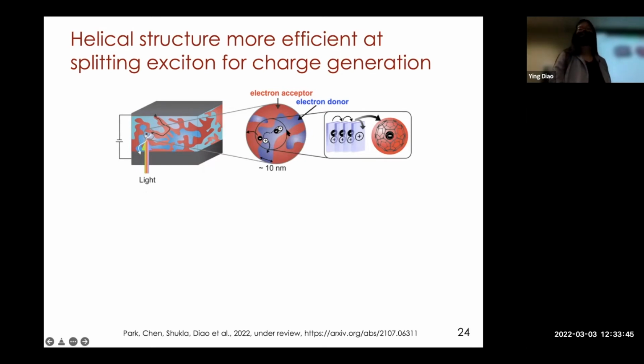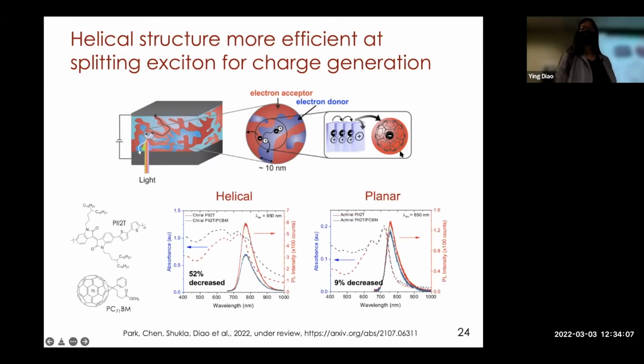And the exciton would, as illustrated here, either recombine to re-emit a photon, or it can diffuse to the boundary of the two materials and split into charge carriers. So we would like them to split rather than recombine so that we can generate electricity. So, because of the ability to tune the helical structures using printing, we were able to compare the helical with planar structure. And we show that, so this is photoluminescence spectroscopy.